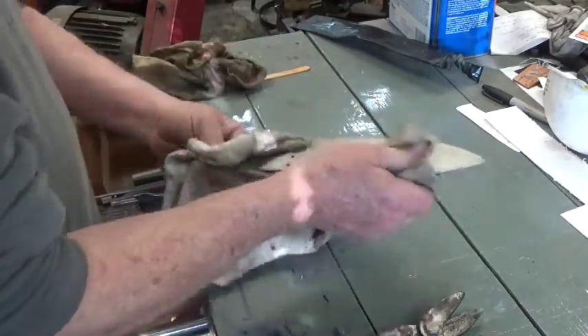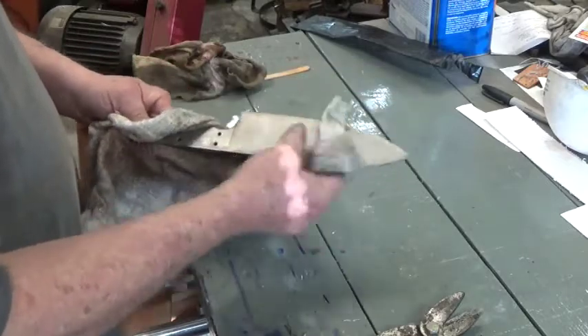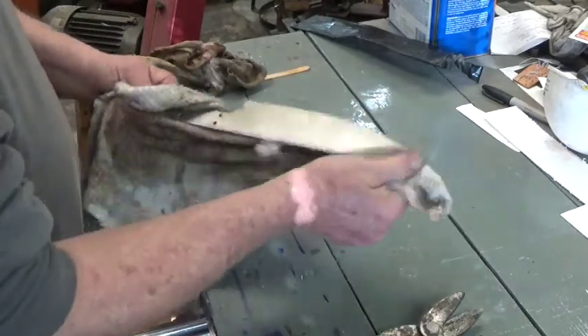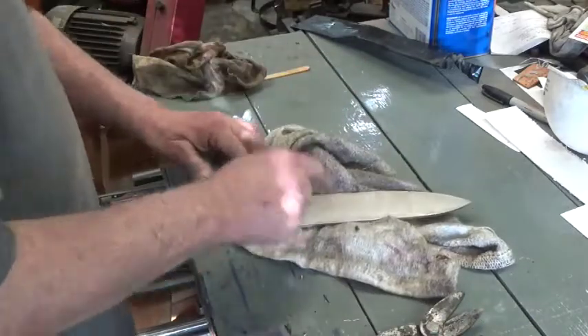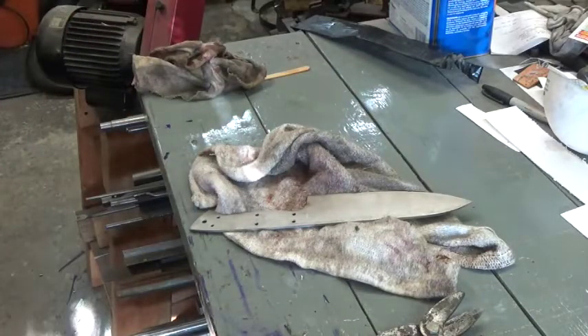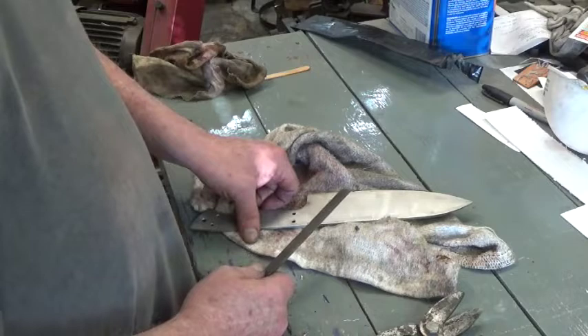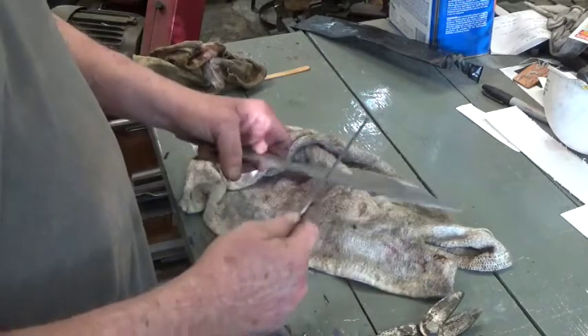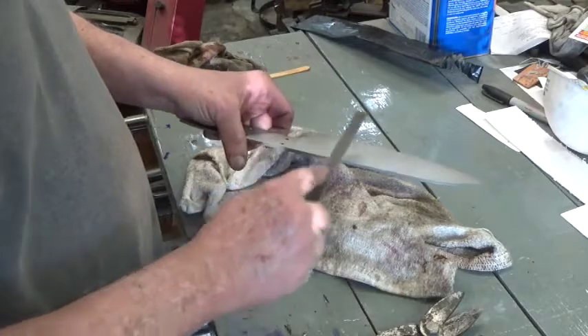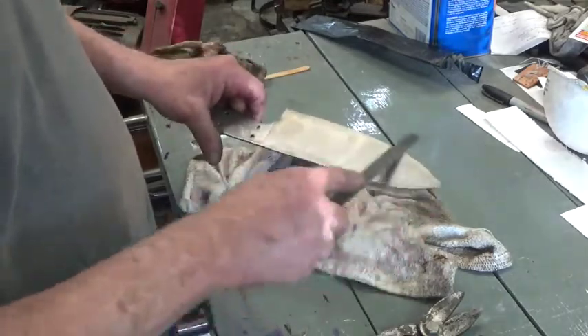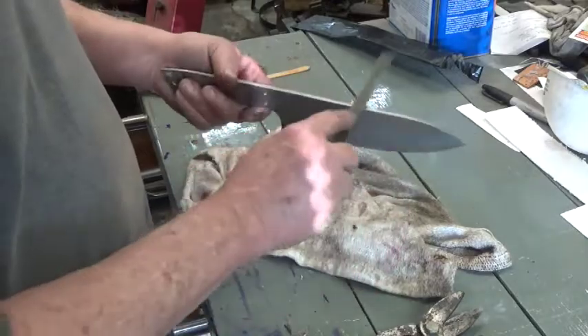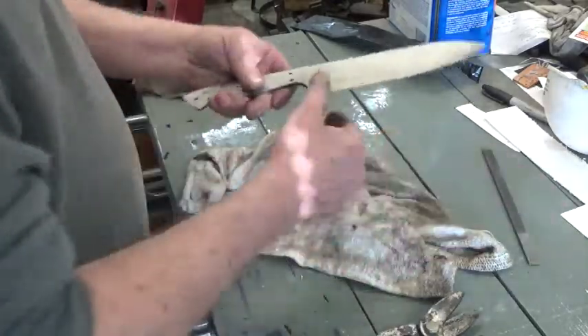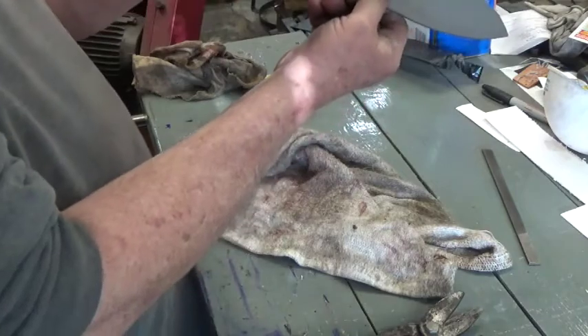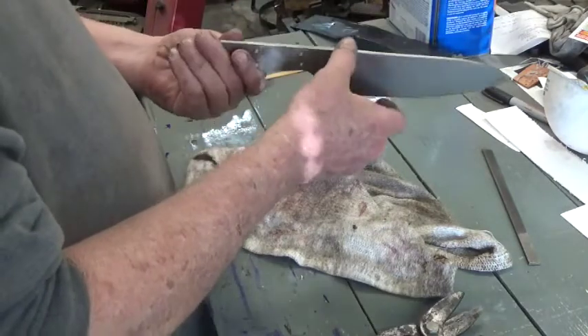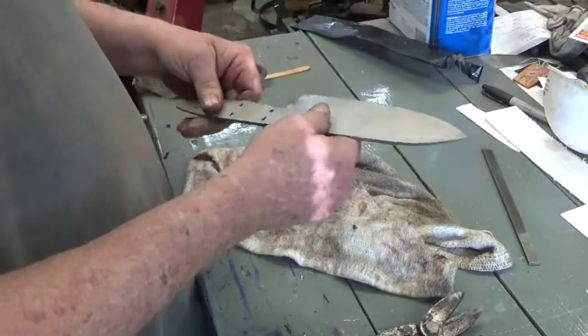This is still pretty warm, but I want to get this into the draw now. All tool steel, you don't want it to sit around in this really hardened state for too darn long. This is not as fussy as O1. O1 can crack just sitting there if you let it get too cold. This is still pretty darn warm. That file won't begin to bite that. Good hard steel. Alright, so we stayed straight in the quench, and the rest of the finish should go pretty nicely, but we have to get this into the draw now.